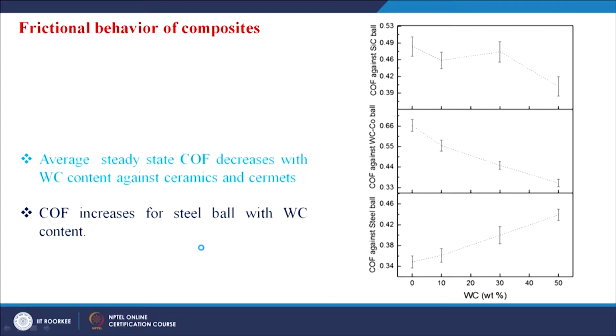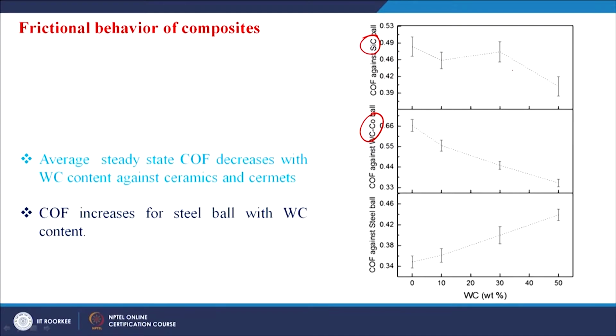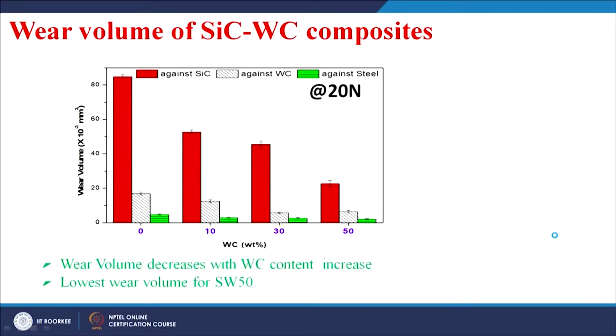So, the friction coefficient shows that the average coefficient of friction actually decreases against the silicon carbide or tungsten carbide cobalt ball, whereas against steel it actually increases because the surface is actually changed at the contact. So, there is a friction behavioral change. Let us understand it further. The wear volume was measured as I explained in the previous class. The profilometry was used to read the surface profiles in a 2-dimensional way, and over a particular slide distance this was integrated and the wear volume was determined.